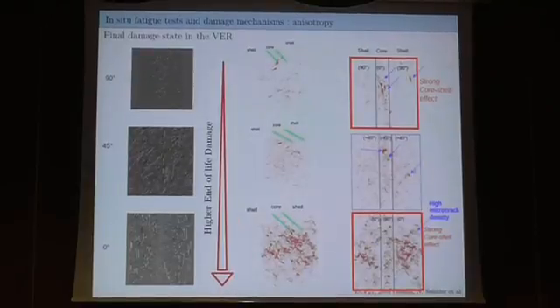The thing is that when you observe the damage at the end of the fatigue test, you clearly see that you have an anisotropy or differentiations that can be made between 0° angle specimen and 90° angle specimen. So for 0° angle specimen, you see that you have a very high density of damage, high density of microcracks, and a strong core shell effect.